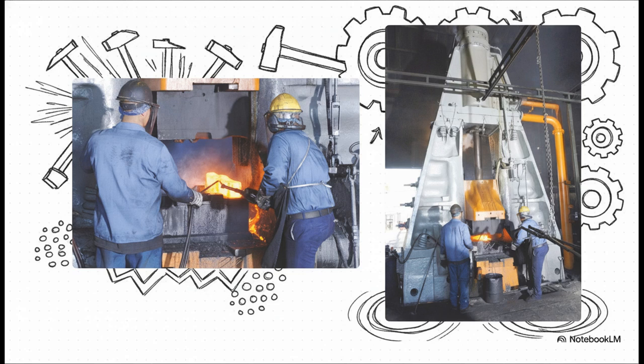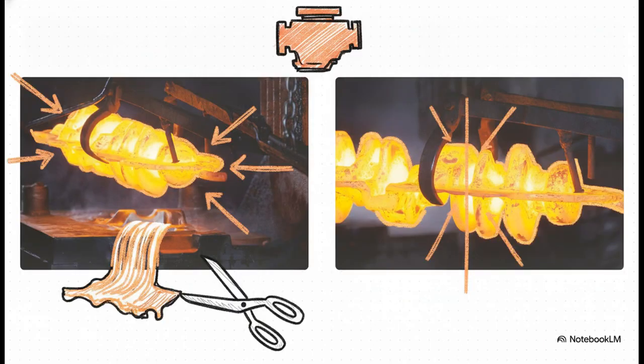It's just controlled chaos. During this violent compacting process, a glowing parting line of excess steel actually gets squished out at the mating lines of the die. It's pretty wild. The raw ingot they start with weighs about twice as much as the final product. So all that extra metal being forced out is completely normal, and they just shear it off in a trimming die later on. If you ever spot a faint trace of this trim line on a finished forged crank, it's just a little cosmetic scar from this incredible process.